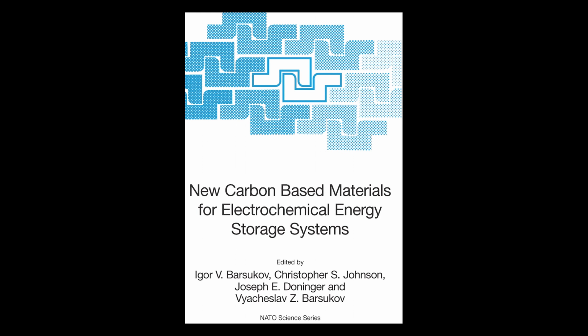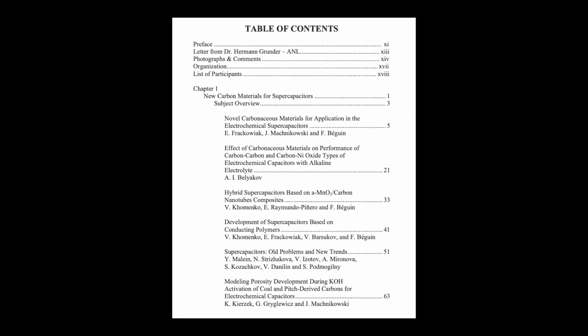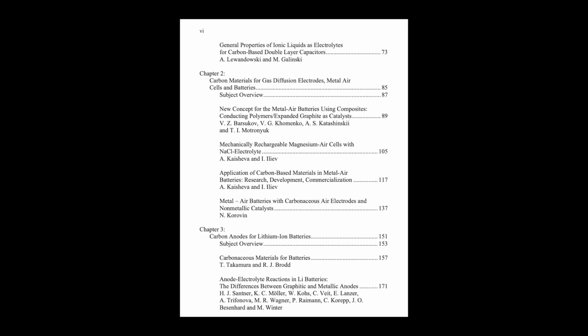So let's talk about that PC problem with graphite. What exactly happens? PC is propylene carbonate. It's a common electrolyte solvent, good properties, relatively cheap. But with graphite, it has this nasty habit of getting dragged into the graphite layers along with the lithium ions. Co-intercalation. And that's bad because the PC molecules are much bigger than lithium ions. When they force their way between the graphene sheets, they pry the layers apart. It's called exfoliation. It physically destroys the graphite structure and leads to rapid failure.